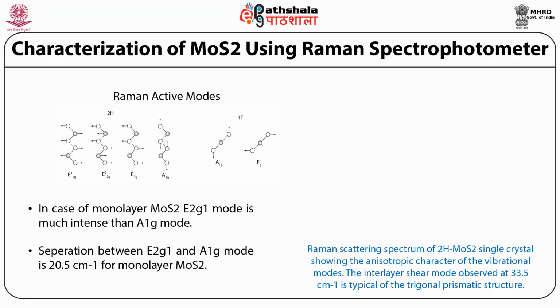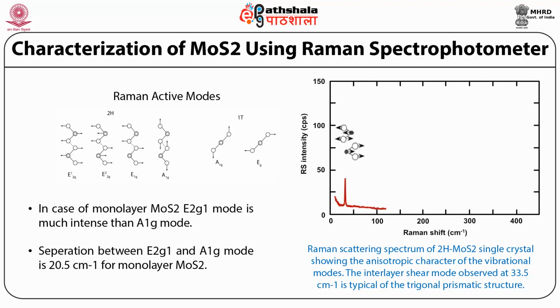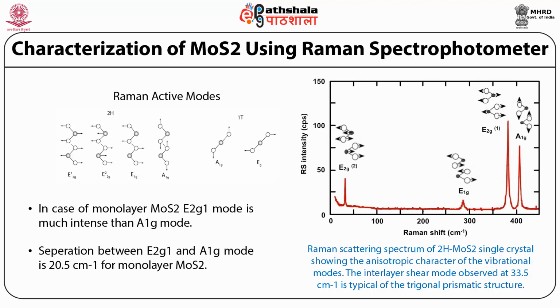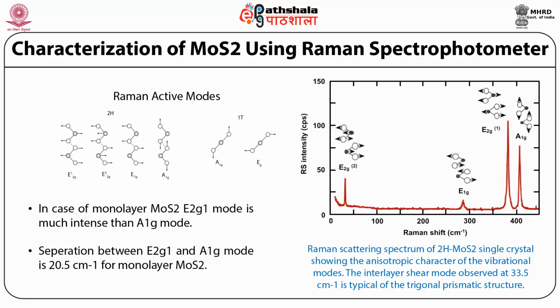I am going to explain the Raman characterization of this TMD sample. Raman spectroscopy is a useful method for fingerprinting a material and layer-dependent changes of the vibrational structure. When varying the layer number between bulk, few and single layer, the Raman spectra differ in spectral width and intensity due to the differing interlayer interactions. The Raman scattering spectrum of 2H MoS2 single crystal is shown in the figure.